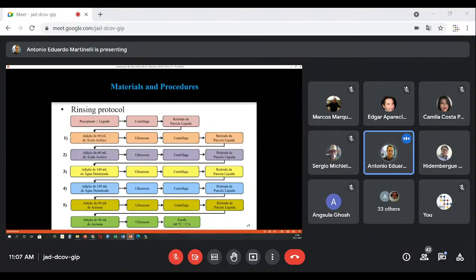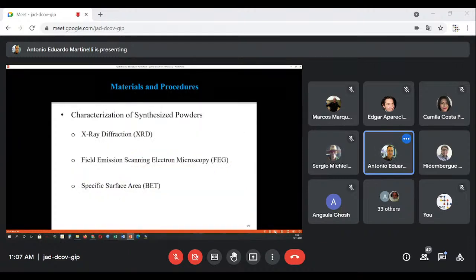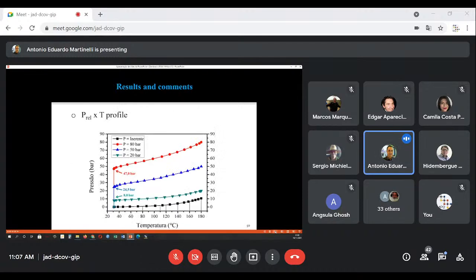So it's a sequence of 5 rinsing sequences. This is our rinsing protocol. And then the powder is kept in an oven at 60 degrees for 12 hours for the final drying. Characterization of the powders took place by XRD, field emission scanning electron microscopy, and BET surface area.